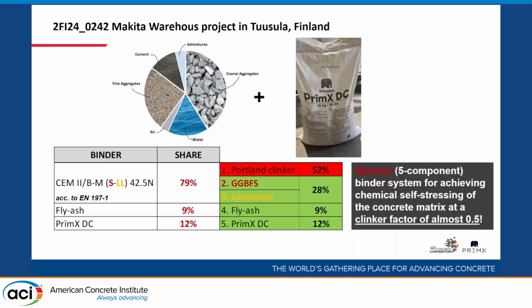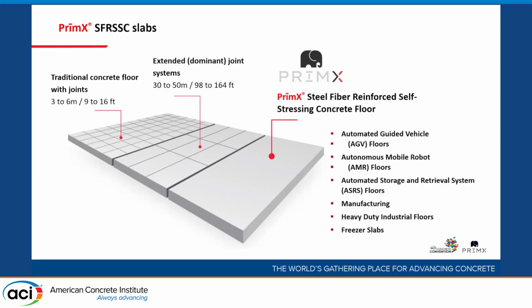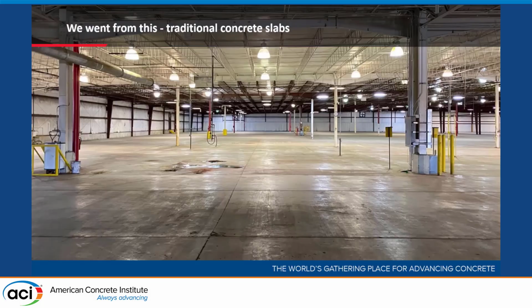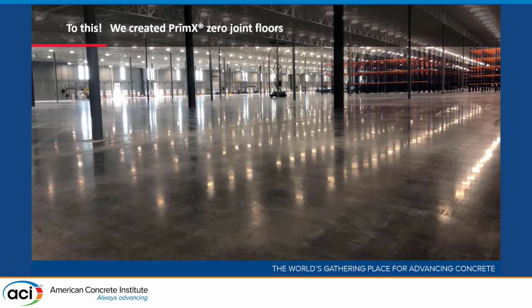Of course, you get some other benefits when you apply it. You can not only reduce the cross-section and by that greatly the embodied carbon, which you can cut further by the Portland clinker reduction, you can also reduce the joints. So in many instances there are no joints at all. And also if there are joints, they are not dominant because they don't open. So from the perspective of the user, you go from joints to no joints at all. How much carbon can you save? 50% is possible, sometimes even more.